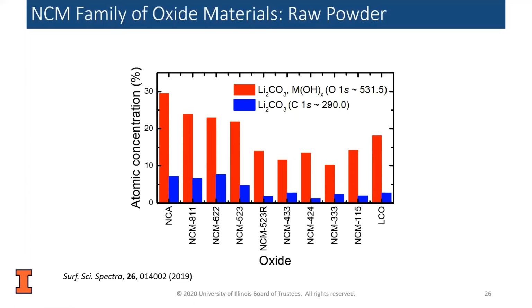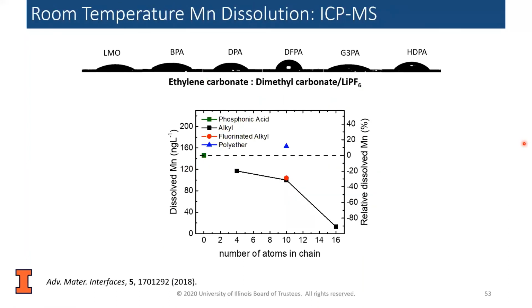Okay, let me go back. We actually did not look at the manganese loss by XPS, because when the batteries are aged, it's almost impossible to see the metal signal. If this is what the person is referring to, in this case we looked at the solvent from a cycled battery and studied it by ICP-MS. By looking at how much manganese was dissolved in the solvent, that was how we estimated the amount of manganese that was lost from the cathode.